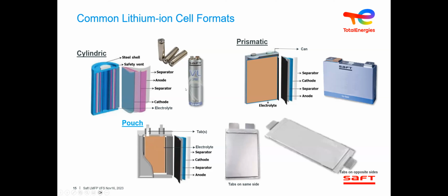You sometimes have issues in a prismatic or a dedicated system like that with a very high mechanical shell around it. Even if you put in a mechanical safety release mechanism, you still have chances to build up pressure and create very high pressure, very strong mechanical behaviors, versus a cell that can release its pressure very quickly and therefore kill essentially its mechanism of thermal runaway.